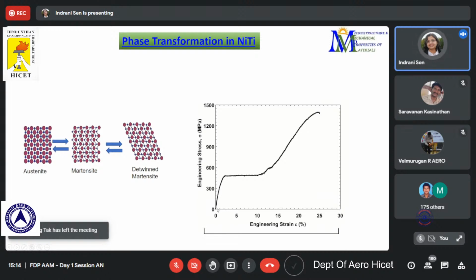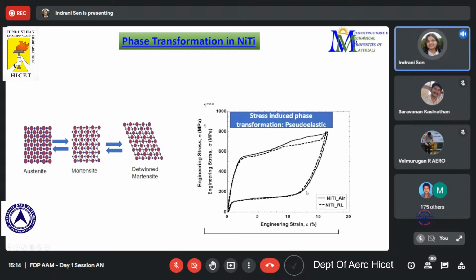You can see the elastic part like any other material, and then the pseudoelastic part and detwinning, etc. If we unload from here, it will come back to the austenite phase, but if we keep on adding stress, it will behave like a regular material. This is like the typical elastic plastic deformation, and it will fracture at a certain point. Whereas if we unload within this plateau region, known as the pseudoelastic plateau, it can regain its shape completely. These are the experimental results that we have seen in our group.